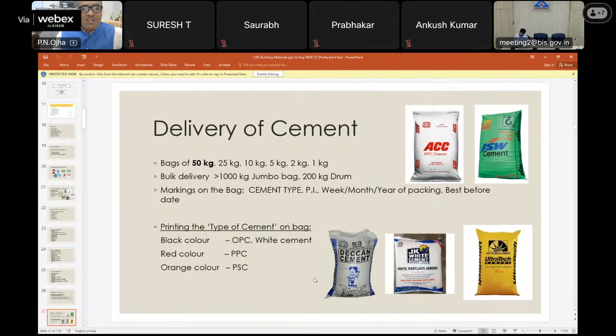Okay, printing of the type of cement, if it is black color, you can see it is in the case of OPC and white cement. In the case of PPC, the writing should be in red color. This is very, very important to recognize from the distance. And in orange color when it is PSC, you can see the bags and the writing color on the bags. So one can recognize which kind of cement, which type of cement is in the bag right from the distance. You will not have to go and see which kind of cement.